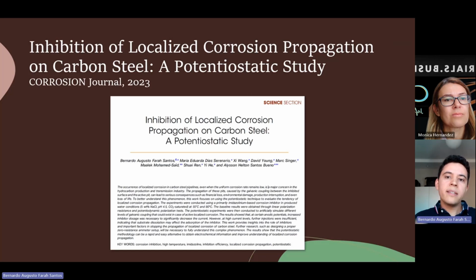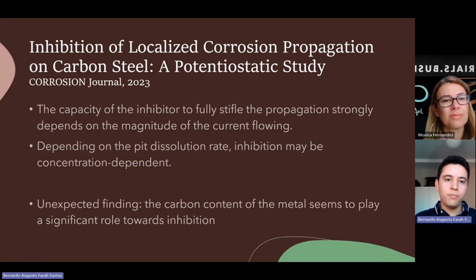So that was basically the understanding that we had, and fortunately we published it recently. It's fruit from my PhD, so for me, it's really important. I'm really proud of it. And just to summarize, the main findings among many others is that we figured that the capacity of the inhibitor to adsorb on the surface, so to mitigate the propagation of localized corrosion because of the galvanic coupling, is dependent on the current flowing.